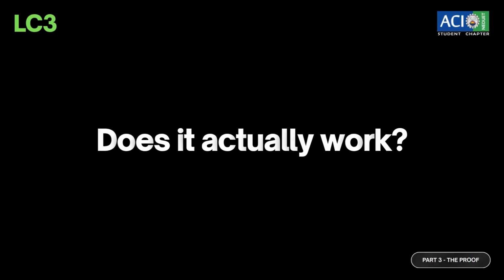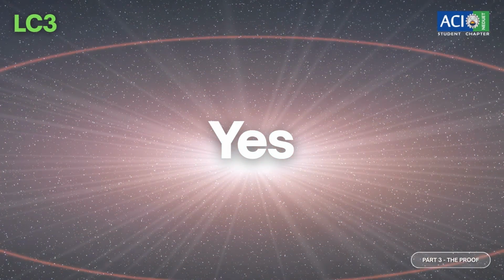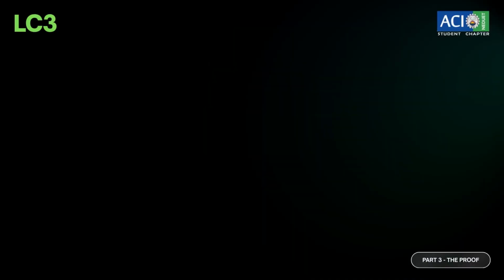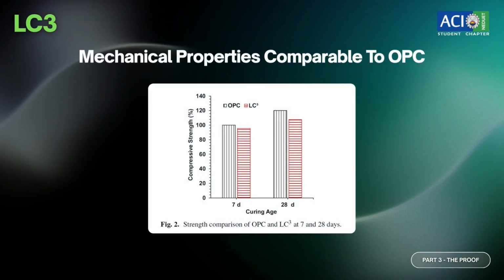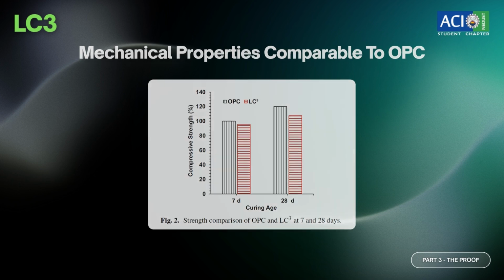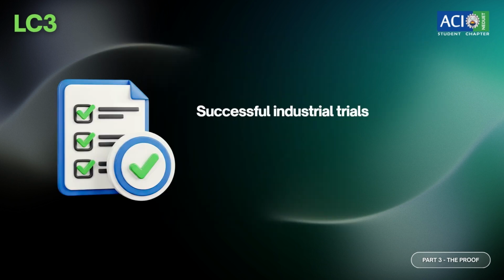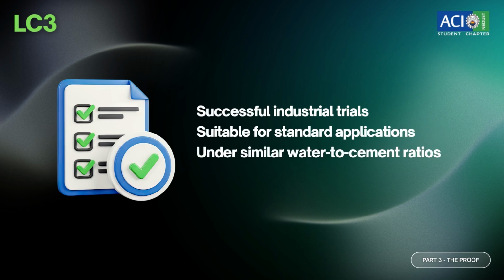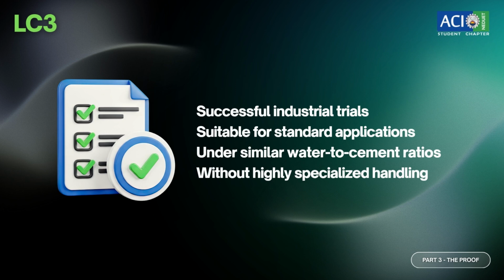And that brings us to the most important question. Does it actually work? Yes. Studies reported that LC3-50 shows mechanical properties comparable to plain Portland cement, with strengths reaching similar levels from about 7 days onward. Industrial trials in Cuba and India have also shown that LC3 can be used in standard applications with similar water to cement ratios and without requiring highly specialized handling. This means LC3 is not only technically sound in the lab, but also feasible in real construction practice.